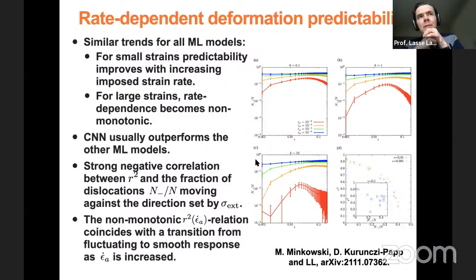Of course, if all the dislocations would just move in the direction that is set by the external stress, then the dynamics would be kind of simple, right? You have just a bunch of dislocations that are all responding in the same way to the external stress, basically. So the interactions between dislocations are not important. And this is basically what happens in the limit of a very high strain rate, because then the external stress is very large, and that dominates the dynamics.